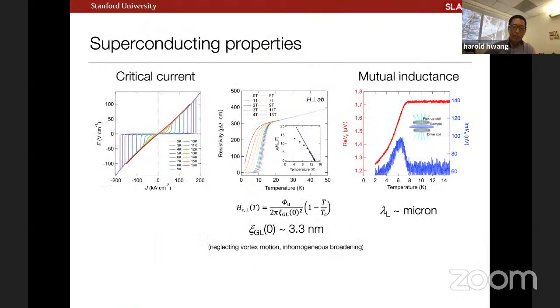In terms of the basic properties that we find at that time, you could see a nice critical current density. I should say that now with subsequent materials improvements, we're at about 1 to 1.5 megamps per centimeter squared. If you take the magnetoresistance near TC as a measure of the Ginzburg-Landau coherence length in plane, it's about 3 to 4 nanometers typically, what I'll show you. And in terms of the magnetic response, we use two-coil mutual inductance measurements. And if there's time at the end, I'll come back to this point. But the details aside, what we then would deduce is a London penetration depth on the scale of a micron or so, quite long.